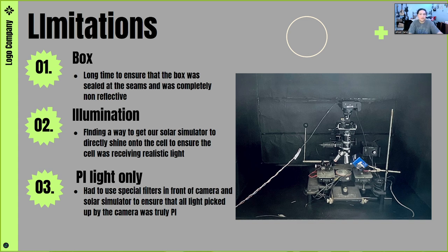And then to ensure that this solar cell was actually being illuminated correctly with realistic wavelengths, we had to attach a light source here. Our original idea was here, but after much effort, we found out that there is a mirror here that negates all of the light that comes in and makes it all one single wavelength coming back up. So it is not feasible to use this part. So we have to do it from outside the microscope, which is the best solution we could find. At a 35-degree angle, we could see the solar cell was completely lit, and no matter what objective we used, we were able to fully light the solar cell.